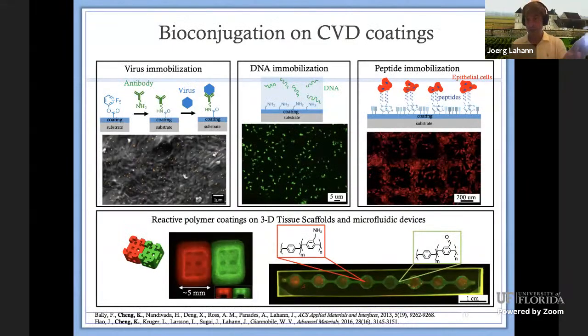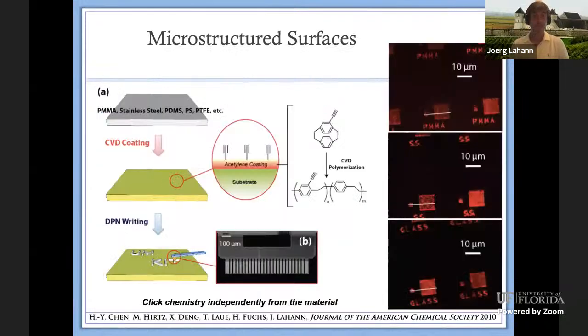Now, obviously, you appreciate that in some of those applications, you're going to think about poly-epsilon-caprolactone biodegradable polymers. So the degradable CVD coating is going to be very handy in this context as well. Here we're going to nanostructures or to smaller structures using AFM. So we're basically doing dip pen nanolithography on those surfaces, again with a click type reaction to immobilize proteins. This is material independent. Here we show it for different types of polymers. Here PMMA, for instance, stainless steel, and even like a glass surface.